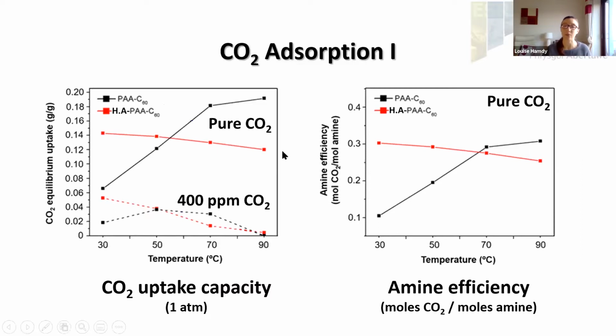We see that the black one here, PAA C60, behaves very typically of many polyamine CO2 adsorbents. Its adsorption is highly temperature dependent. At 90 degrees, we get the highest uptake of about 0.19 grams per gram, but at 30 degrees, which is relevant to our direct air capture conditions, around about ambient temperature, the uptake is far lower at about 0.067 grams per gram. Now, this is due to the diffusion limitation of this material.